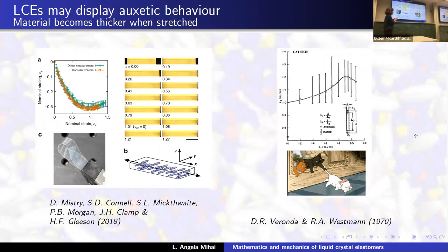That's not only a curiosity. A different type of liquid crystal elastomer has a different behavior. Namely, when they're stretched, like one would expect in simple tension, it was observed that the thickness of the material at some point decreases, as it should, for a while, but then suddenly it becomes stationary and then it tends to increase a little bit. So it's a kind of auxeticity that's observed here, because in auxetic materials, you stretch them and they become wider instead of becoming narrower in the orthogonal direction. It's the same here. So this material, you see, is transparent.